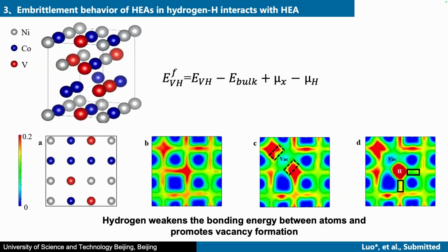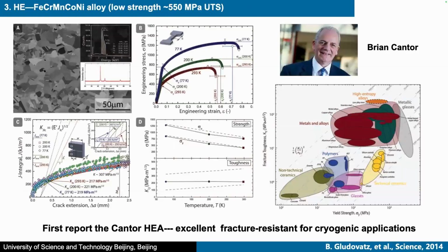Also, we did some DFT calculations on how hydrogen can weaken the bonding energy between the atoms, and we also found that it can promote vacancy formation. This is previous work.